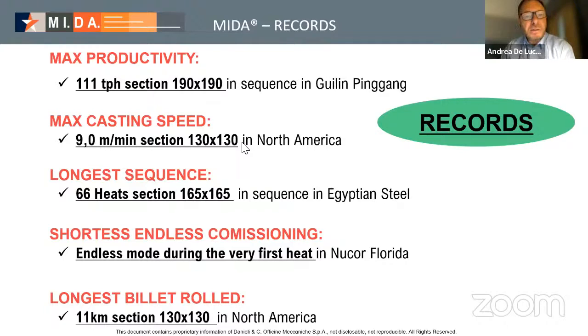The MIDA technology works on very long sequences without any change of the refractory tundish. So the same configuration, the same refractory works, for instance, in Egypt, up to 66 heats with the section 165. So imagine hours and hours without any head or tail entering the mill. So this is improving the efficiency of the rolling mill.